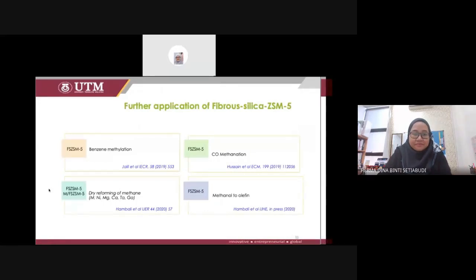And then we tried to modify with other zeolite. No, we try to apply the fibrous silica ZSM5 on other reactions instead of cumene cracking. We also successfully produced toluene from benzene and methanol, as reported in our paper in 2019 in Industrial and Engineering Chemistry Research. And then we also reported the successful use of fibrous silica ZSM5 on CO methanation in Energy Conversion and Management.